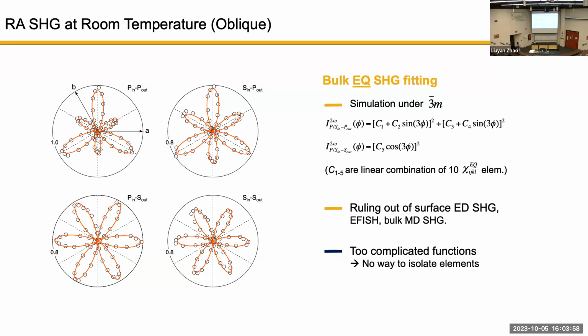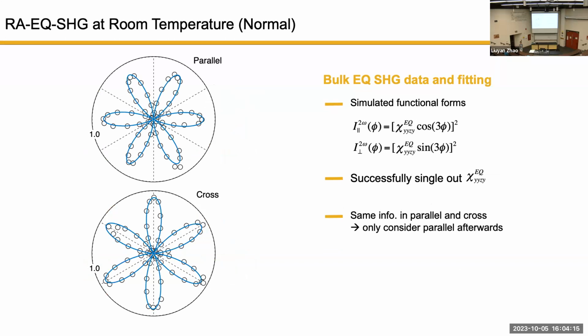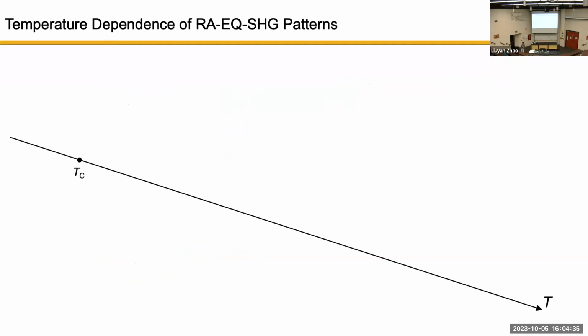So then from the simulation, we see that the coefficients are actually pretty complex. You have five coefficients, and these five coefficients are actually linear combinations of 10 parameters. That's too complicated for us to see the physics. So then we make the experiment simple. Instead of doing oblique, let's do normal. Once we do normal, you can see that we can pick out one element in particular to look at. So looking at one element makes our experiment collinear. Okay. So then these are the so-called parallel and cross channels.